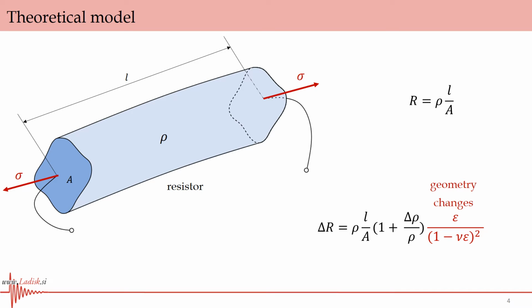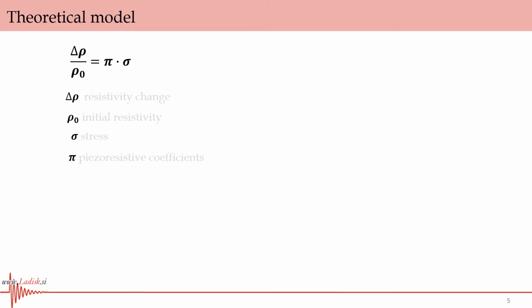In structures with strong piezoresistive effect, change in resistivity is dominant and is therefore more interesting for the observation. Material model of piezoresistivity is similar to Hooke's law and is for anisotropic material expressed in matrix form. Here, quotient between resistivity change due to stress and initial resistivity when no stress is applied is related to the mechanical stress through the matrix of piezoresistive coefficients.